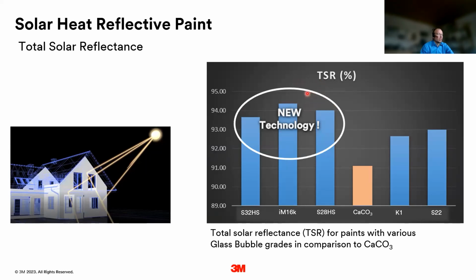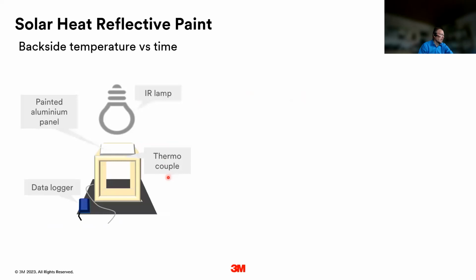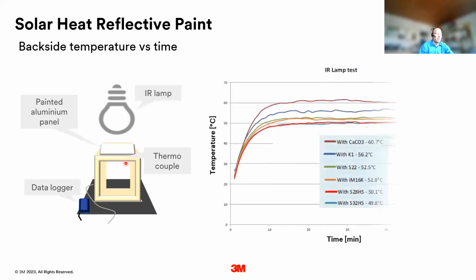And to show you what effect this will have in a real application, we installed this very simple test setup. Actually, it's an infrared lamp, and then we prepared aluminum panels that were coated with the different paint formulations. And then on the back side of this panel, we have a thermocouple with a data logger. And then after switching on the infrared lamp, we were logging the temperature.